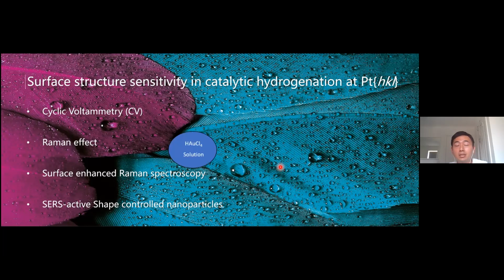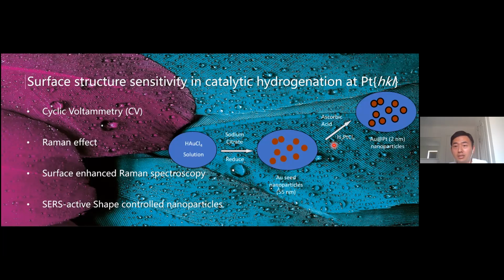So how do we make these nanoparticles? We can make gold-platinum nanoparticles with a 2 nanometer thin shell around gold. Also, if we replace the platinum shell with silica, we can make this type of nanoparticle. Later I will show how important these are.